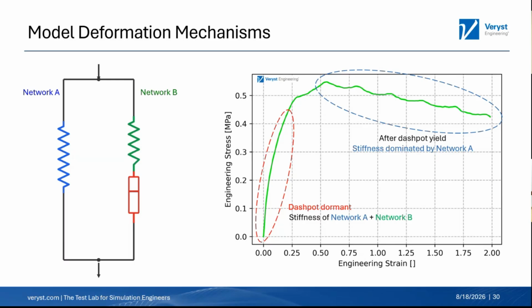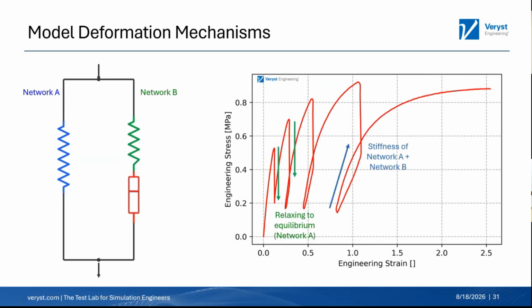And that's why we get that kind of response. And as we start to talk about cyclic behavior, I've taken that red curve there, and again, I'm trying to show what happens. So as we load this up, remember at the beginning, we're loading up, we've got the stiffness of network A and network B, and then we do a stress relaxation and we hold it.